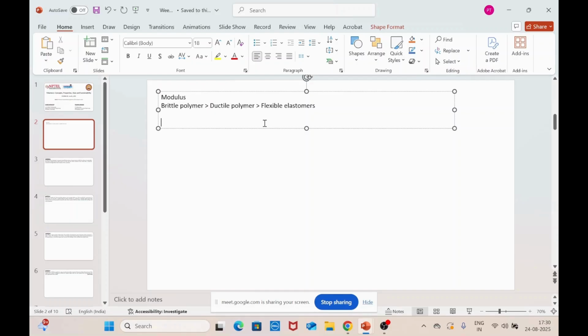So if you see in case of brittle polymer, as I previously discussed, even if you increase the amount of stress to a very large extent, the strain developed in the material is very small. By Hookean law, modulus can be defined as the ratio of stress to strain. Everybody must have an idea of the Hookean law, where you consider your material as an ideal spring, and based on that you can write this equation. So for a brittle polymer, stress will be very high, but for that high stress, the strain developed in the material will be very small.